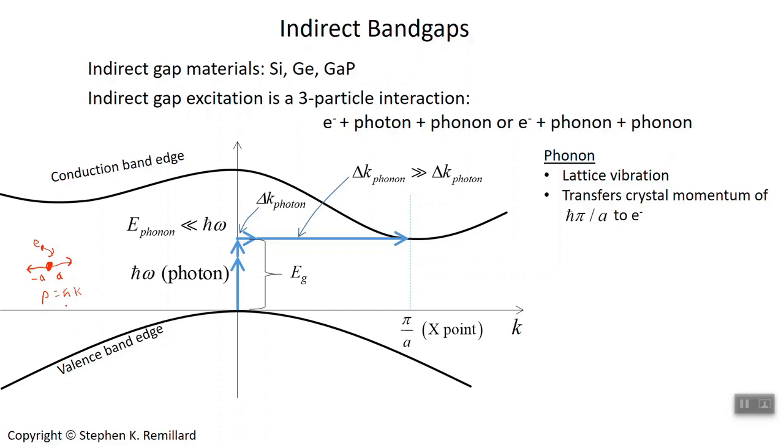So it can get a delta momentum of h-bar times delta k. The k is 2 pi over the vibration amplitude. So we can say k is 2 pi divided by A. And so the momentum kick is h-bar times 2 pi over A, where the delta k that the electron will experience is 2 pi divided by the lattice constant. What the electron is actually doing is receiving crystal momentum from the phonon. I'd also like to point out this pinball machine analogy. When a pinball hits a bumper, it receives an impulse because of a spring-loaded mechanism inside the bumper. The electron hitting the atom, think of the atom as the bumper in a pinball machine. The atom is spring-loaded. That spring-loading is the phonon, and it delivers a bunch of impulse to the electron.